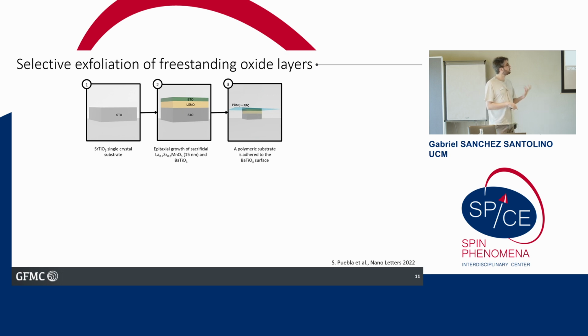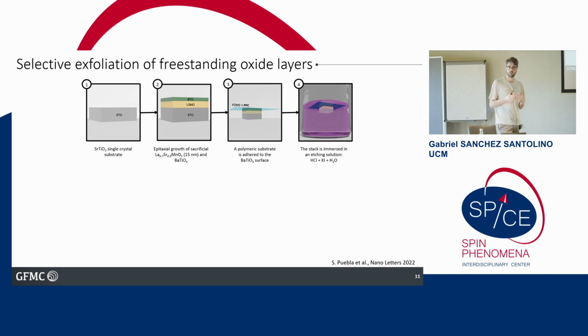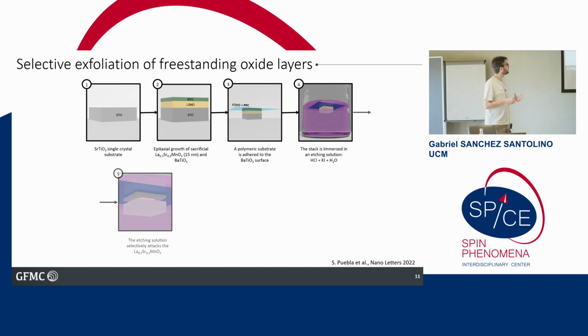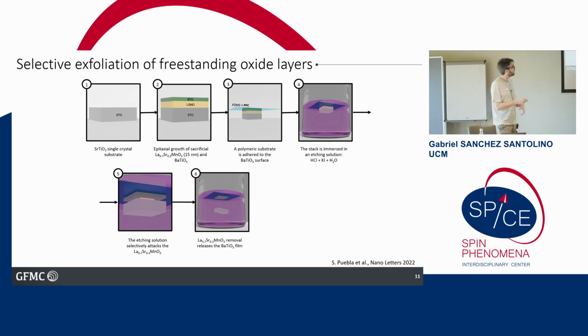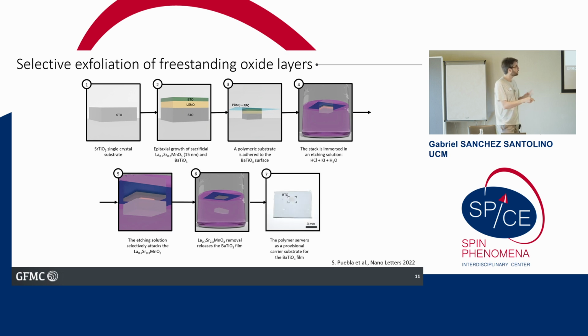and we are going to submerge this structure in a glass with an acid that is going to selectively etch the manganate layer. So this acid is only going to etch the manganese atoms. It's going to remove this layer, and after a few hours or maybe even a few days, we are going to end up having our ferroelectric epitaxial layer stuck to the polymer, and our substrate will just drop to the bottom of the glass. So we can have this kind of 2-dimensional ferroelectric layer on our polymer.